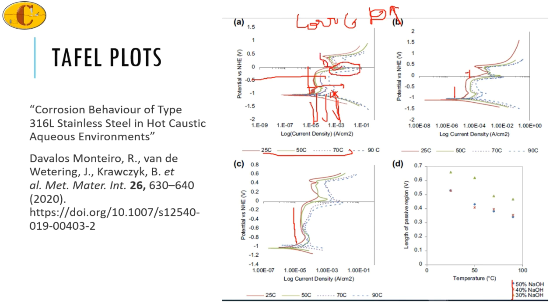This is the secondary passive region. Secondary passive region means you will have another short passive film formed at the top. So when you are going to higher potential and higher concentrations of NaOH, the secondary passive region is also changing. So electrochemically, it means that the corrosion rate is also going to be modified with respect to the concentration of NaOH. So this means that when you are talking about the caustic service chart, you will also have to see these kind of corrosion rates at those particular temperatures and those particular concentrations.